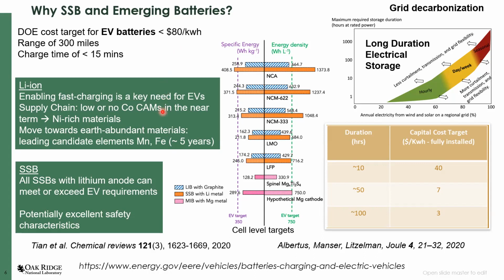As I said, we have to be using materials that are quite prevalent in the crust of the earth. We want to go away from things like cobalt. So in the near term, the approach has been to use nickel-rich material. It turns out that lithium nickel oxide can also be used as a battery material. So there is an approach that has been taken to go towards nickel-rich materials.